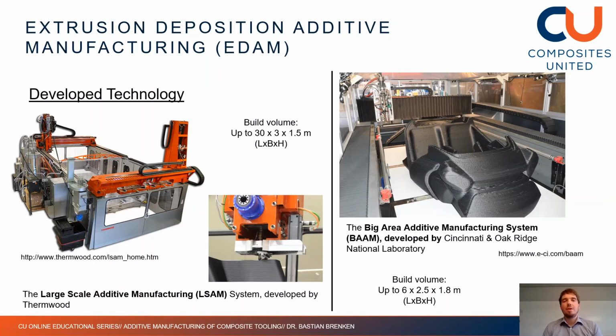What's very special about it is that you have two gantries that you can see. On one you have a single screw extruder mounted vertically, and you print with this gantry. On the second you have a CNC mill. So without having to change the position, you can first print the material and then machine it down to size. And the machining step is required because for a tool and also for many other parts, you want to have smooth surfaces in the end. If you deposit lots of material with a large bead diameter, the surface roughness of the walls becomes significant. So you need smooth, flat surfaces with a low roughness, and for that, you need to machine after the print.